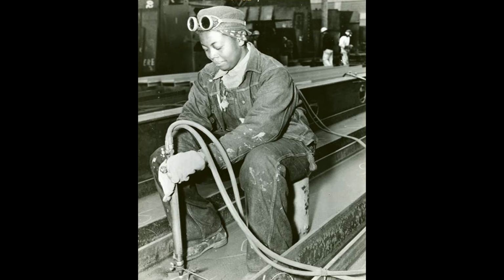By October 1943, statistical analysis of weld defect rates across Kaiser's 7 shipyards revealed a pattern that the Maritime Commission could no longer ignore. Yards that had most aggressively adopted downhill technique showed rejection rates of approximately 4.2% of completed welds. Yards still primarily using orthodox uphill methods showed rejection rates of 7.8%. The forbidden technique wasn't just faster, it produced fewer defects that required repair. The ships were being built better as well as quicker.